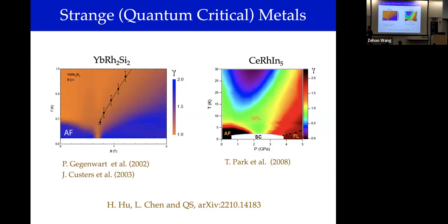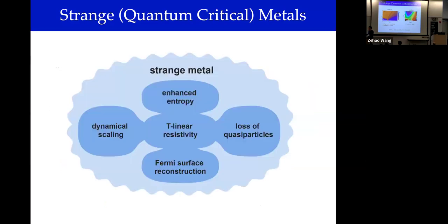And that's a hallmark of the fact that the exponent is different from 2, either here, the blue ones, or the black and other colors representing gamma equals 2. That signifies a potential, at least a candidate system for the breakdown of quasi-particles. But other quasi-particles really lost.